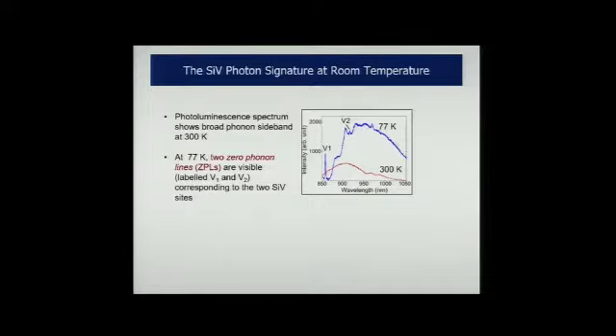There's almost no signal that you can discern. All you see is this broad peak, which is what we call a broad phonon sideband. There's nothing distinctive. There's no clear signature of a transition that's associated with the silicon vacancy.